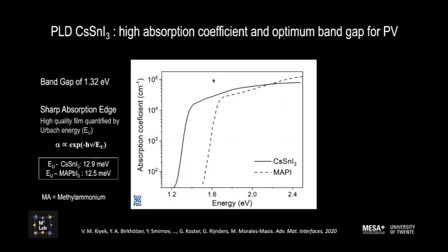And then, of course, you also have to check the functional properties. So this is the absorption coefficient of the material, which you can see in the plot here, where you see the absorption coefficient versus the energy. And you can clearly see that it is quite different from methylammonium lead iodide, and you see a very sharp absorption edge there with a low value of the Urbach energy. So that also tells you that the film quality is quite good, so that you have fewer defect states in there. So it worked out quite well, and it has been published, as you can see in the reference below.